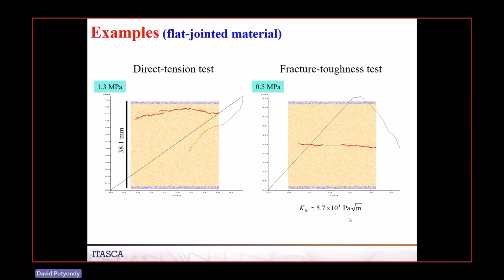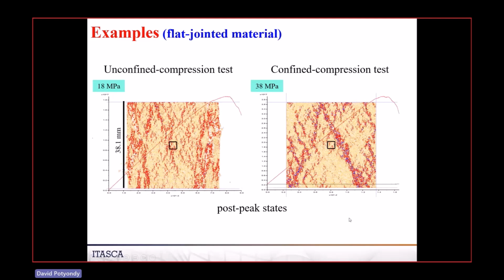There it is. We do an unconfined compression test. Here's all the damage we see. 18 MPa. We do a confined compression test. There's the higher thing. Notice you're getting these shear band-like regions in here. Notice the blue, that's the micro shear failure. You're shutting down the ability for the thing to axial split in tension. So therefore, it ends up forming these shear bands.